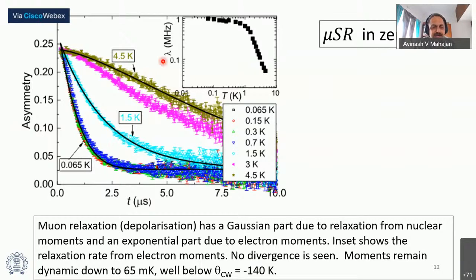It's also sensitive to the nuclear moments. Here, of course, you have copper and antimony nuclear moments also present, and it's sensitive to those also. The characteristic behavior because of interaction with nuclear moments, which are really paramagnetic all the way, is different from interaction with local moments from the electron. So the high temperature behavior here, high temperature being 4 K or so, is characteristic of relaxation due to nuclear moments. So these muons are relaxing, they are getting depolarized. As you implant them, they are fully polarized because that's how they are produced.